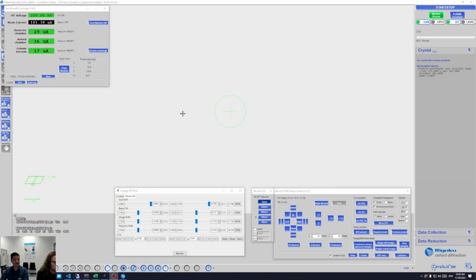So now we see this CAP user interface. You see that the pump down has now fully completed of the airlock chamber, and we have inserted our sample into the vacuum. So Kai will now turn the beam on. The beam is turned on by engaging a heating filament on which the LaB6 crystal that emits the electrons is placed, which is now heated to, I think, approximately 1800 kelvins.